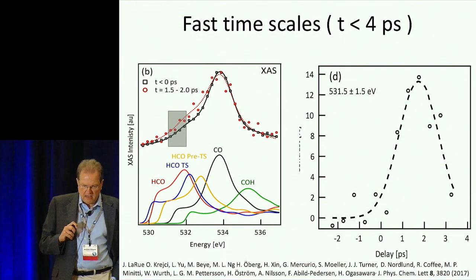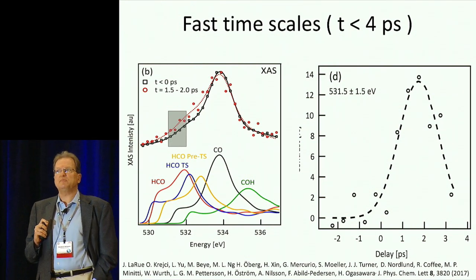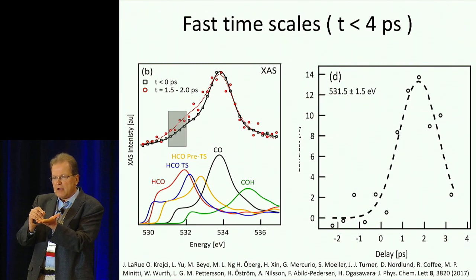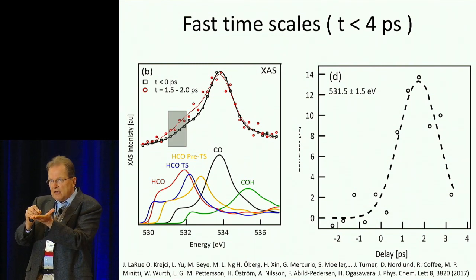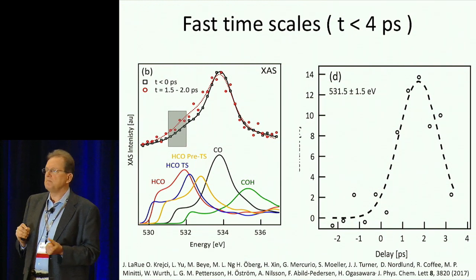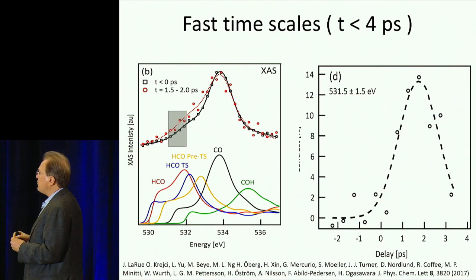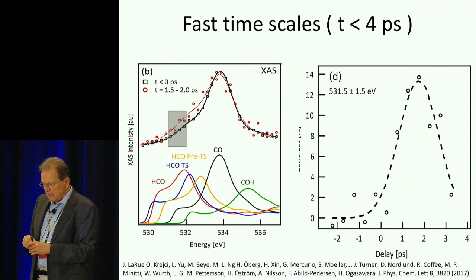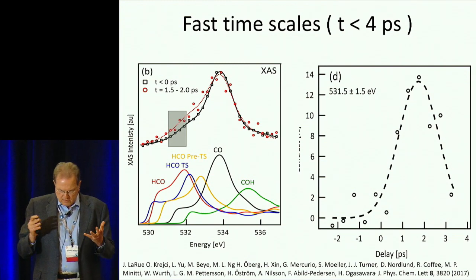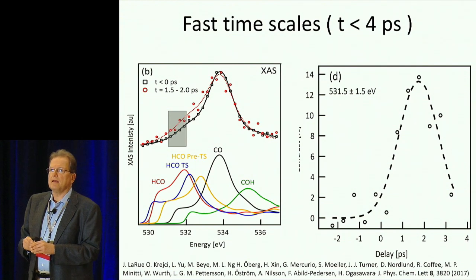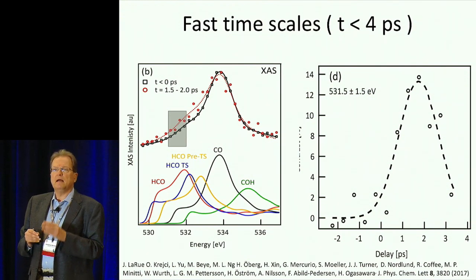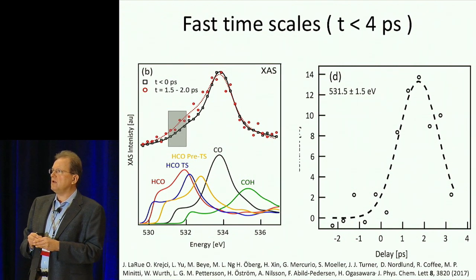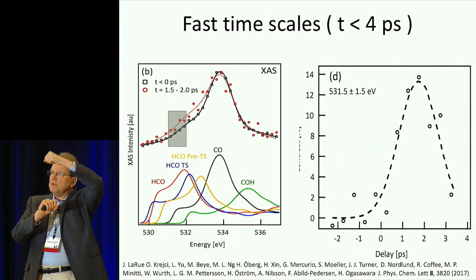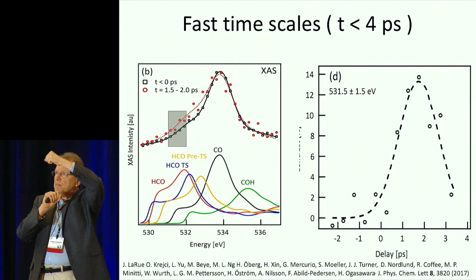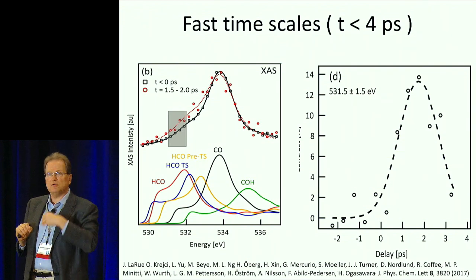And what you see on the left here is spectra, what is called X-ray absorption spectroscopy. It means that we are taking an electron in the core of oxygen 1s and lifting it up into the unoccupied states. So what you see there as the strong resonance on the left side, which is actually the black spectrum, is CO on, in this case, the ruthenium surface before you put in an optical pump. And the resonance you see there is called the 2 pi star level, which is the antibonding orbital between the carbon and the oxygen of the pi system, antibonding because it's unoccupied.